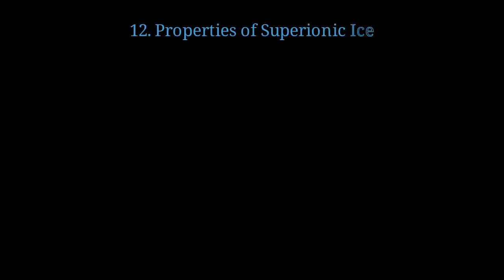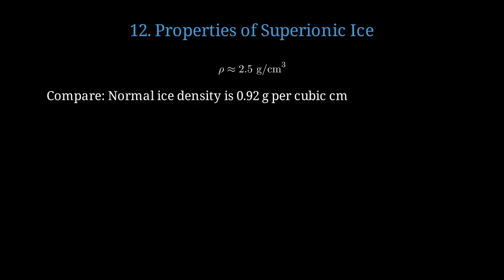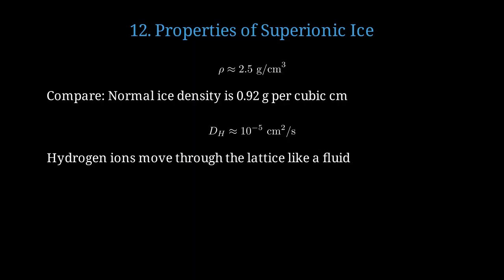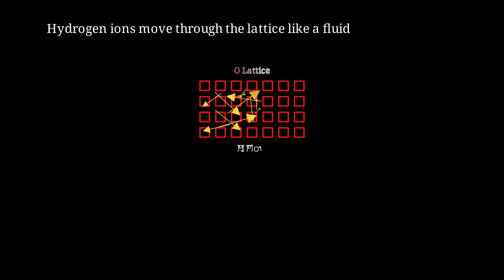Let's quantify some key properties of Superionic ice. Superionic ice has a density of about 2.5 grams per cc, which is more than twice as dense as normal ice. Compare this to normal ice, which has a density of 0.92 grams per cc and floats on water. The hydrogen diffusion coefficient is about 10 to the minus 5 square centimeters per second, indicating very mobile hydrogen ions. This means hydrogen ions zip through the oxygen lattice almost as freely as molecules in a liquid, despite the solid structure. The oxygen atoms form a rigid grid, while hydrogen ions flow freely through the channels, creating this dual solid-liquid behavior.